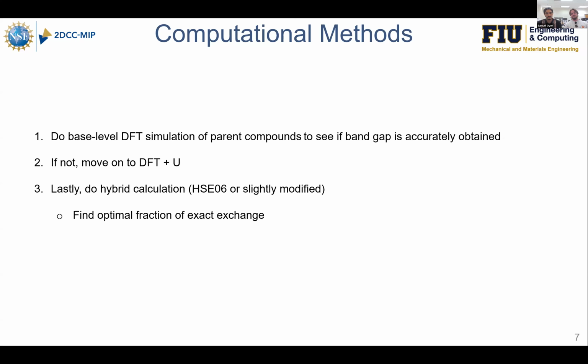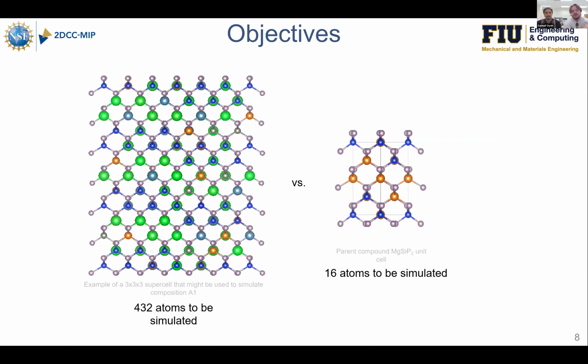And lastly, if we're still not able to reproduce the desired properties, we move on to hybrid functional calculations, which are very resource intensive. So when I was talking about the resource intensivity of these calculations, this is just a comparison of one of our compositions compared to the parent compound MgSiP2. We can see there's tens to hundreds of times more individual atoms that would need to be simulated in the unit cell. So it's pretty obvious why, in the time constraints that we had, it wasn't exactly possible to calculate the high entropy material itself. And additionally, you wouldn't be able to just run this calculation once. You'd likely have to run it several times and take the average of those values.